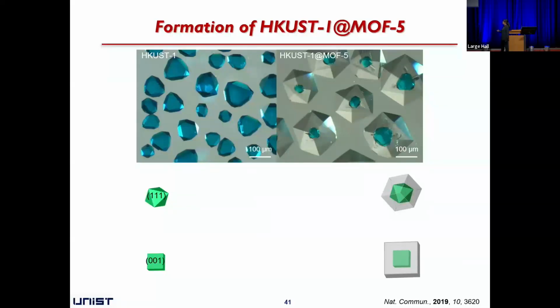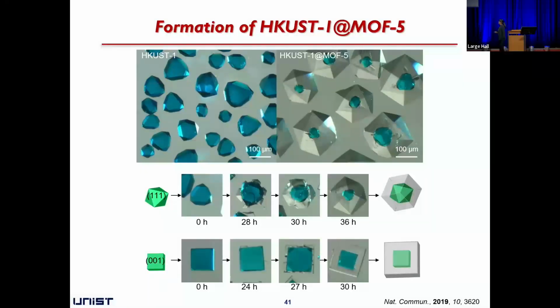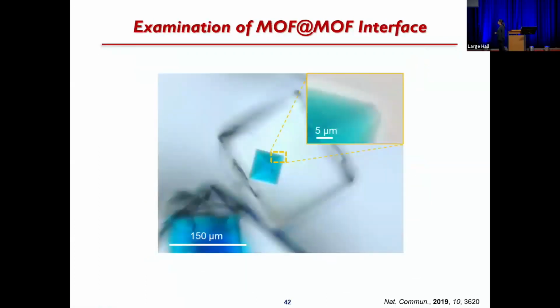Okay, so we prepare the octahedron and cubic shape HKUST-1. Then if we grow the MOF5 as a shell, as you can see here, we can obtain the single crystalline MOF-on-MOF structure, HKUST-1@MOF-5 core shell structure. If you see more detail at the structure of an interface, okay, as you can see here, it is a very seamless interface. And if we try to crush this crystal through this interface, we cannot even do that. It behaves like a single crystal. It means that at the interface, the MOF-5 and HKUST-1 make a very strong coordination bond.